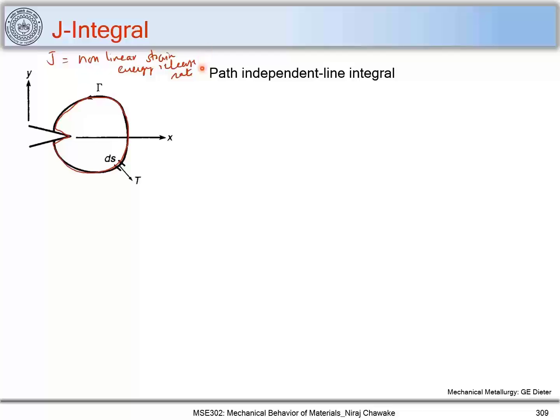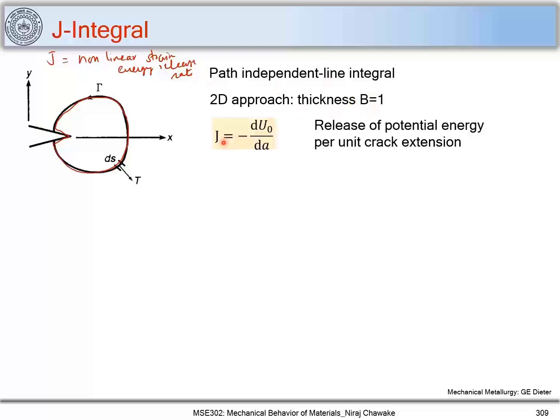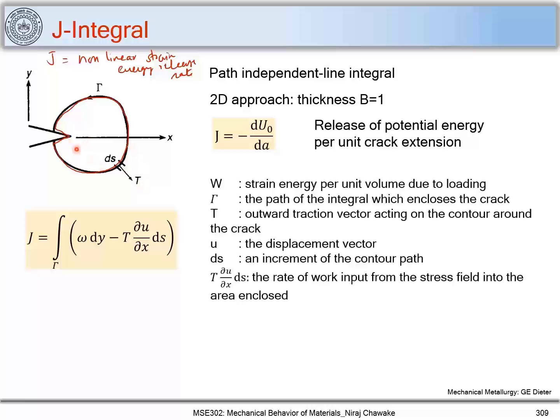Now we'll go with the same methodology by which we found G, the linear strain energy release rate. So let's consider this to be a 2D approach. Consider the thickness to be equal to 1, and we find J to be equal to minus dU naught upon dA, where when this crack extends, there will be a release in the strain energy. So we call it the release of potential energy per unit crack extension. You can find it by using this line integral over this line segment, gamma. And when the crack extends, there will be a release of strain energy. Also, you have to do some kind of work, which is given by this. This total value will give us the change or release of potential energy per unit crack extension. So this term will give us the strain energy per unit volume due to loading. This gamma, which is nothing but this path, must enclose this crack.